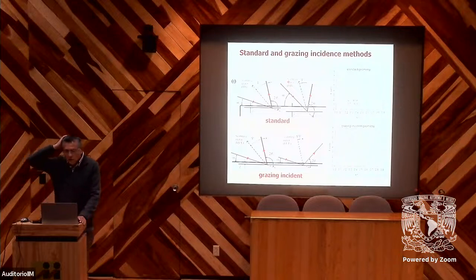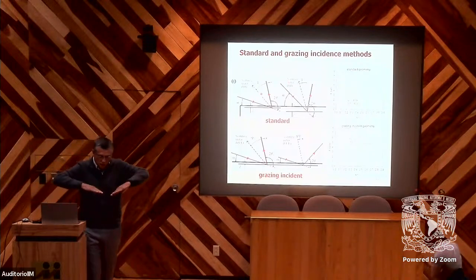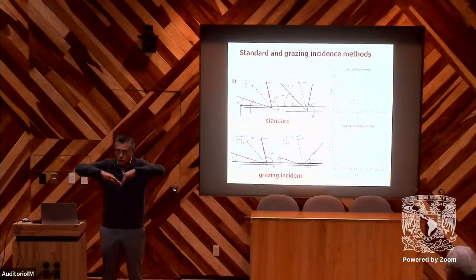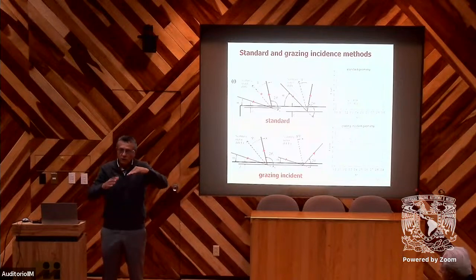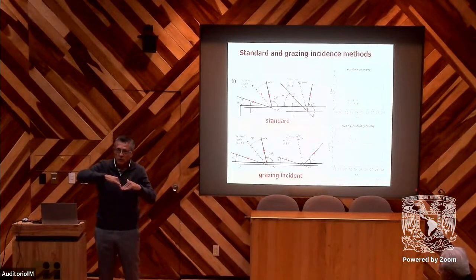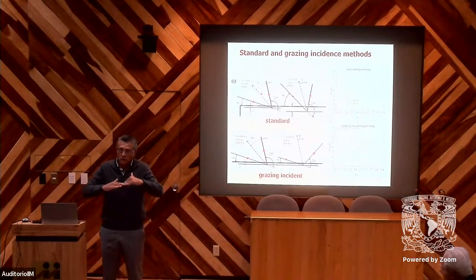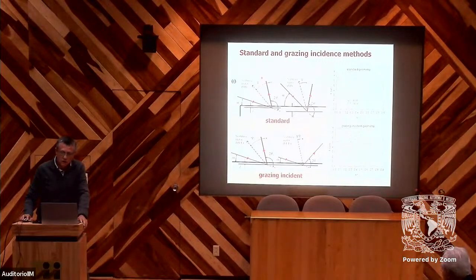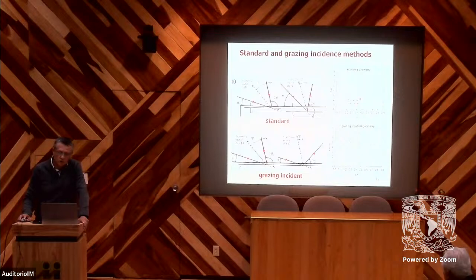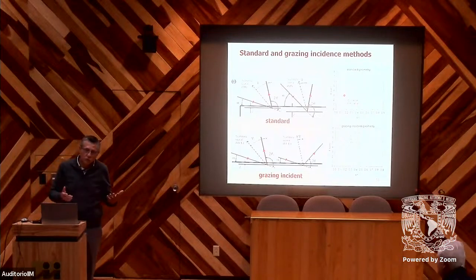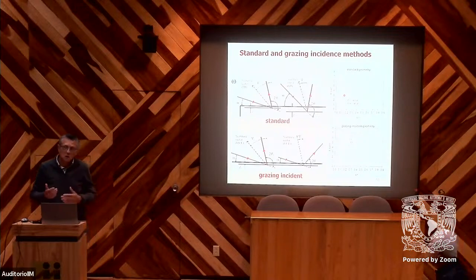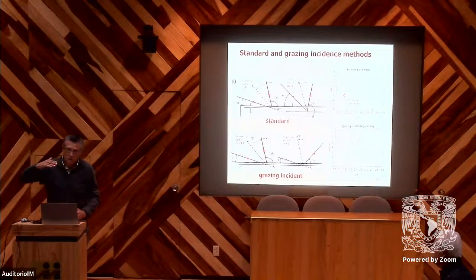Yes. So in the standard method, you have the incident beam and the diffracted beam. And to make a measurement, you measure always in the normal direction to the crystals. So that means if you want another direction compared to the piece, you need to tilt the piece as you wish, and that means you change this angle psi. This is the tilt. And if you change the tilt, you also change the penetration. This is the standard method. With the standard method, you have to determine an average. For example, if you make a measurement for steels, penetration is about 6 to 10 micrometers. This is the average.